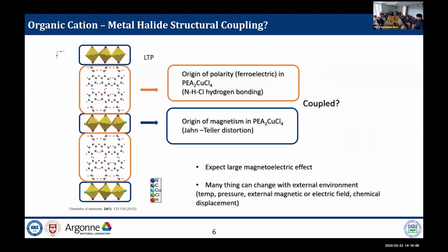So these materials also have unusual magnetic properties, such as quasi-two-dimensional Heisenberg ferromagnetism in PEA2 copper tetrachloride and antiferromagnetism in PEA2 manganese tetrachloride. This comes from the metal halide octahedra, and especially in the copper case there is a Jahn-Teller distortion. The room temperature ferroelectric ordering comes from the organic cation, especially the NH-Cl hydrogen bonding. So my suggestion is that the magnetic and electric properties are coupled with some other factors, such as structure or other chemical bonding.